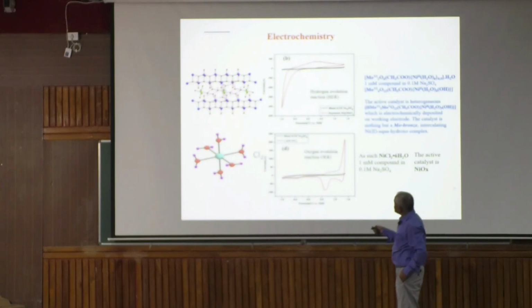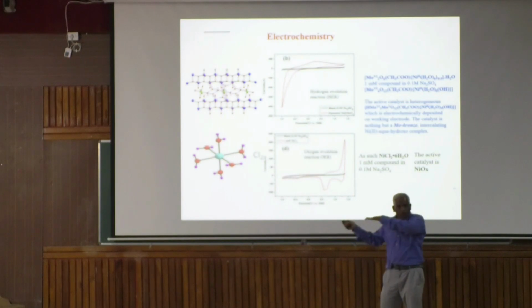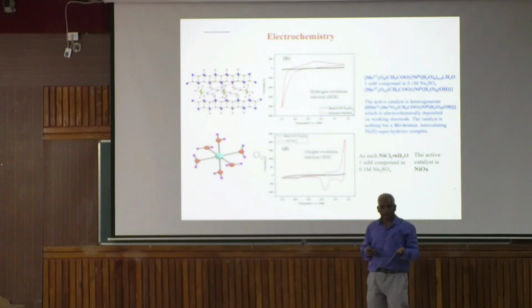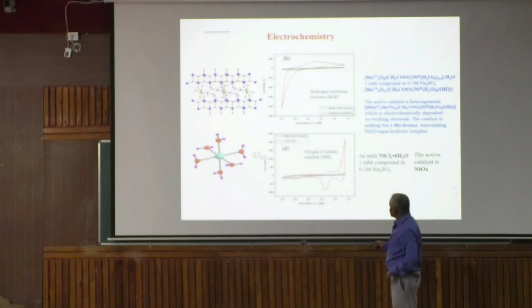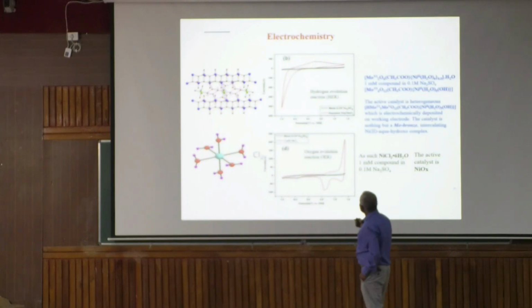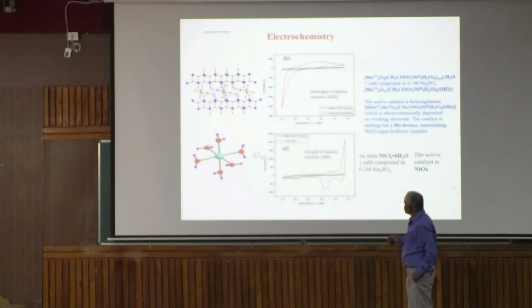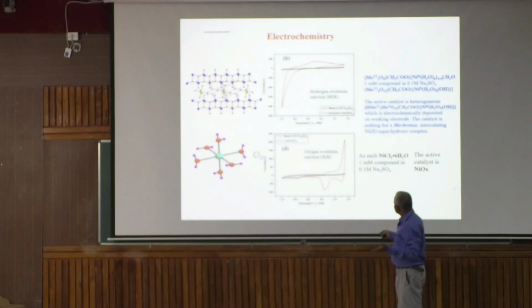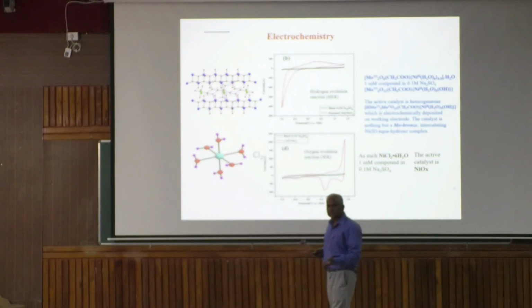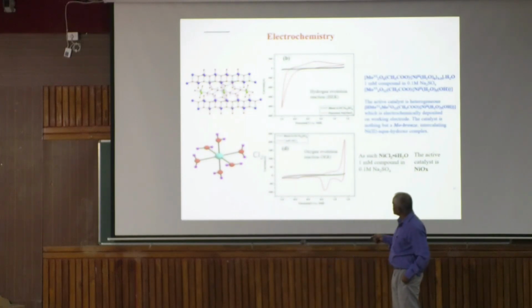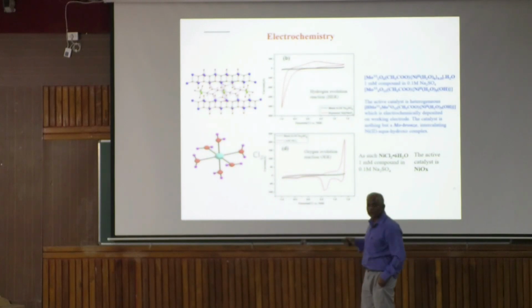Once it is intercalated in the MoO3, the compound you got is likely also water soluble. I told you pH goes down. When we do CV, what did we find? Completely a miracle. This same species giving water oxidation, here we get continuous hydrogen evolution. It doesn't give anything on the anodic side, it gives only hydrogen. We measured by GC-MS, it is hydrogen, definitely. Then why is it happening? Because here nickel 2 goes to nickel 3, 4. Why is it not going to nickel 3, nickel 4, not water oxidation? Instead, we get hydrogen evolution.